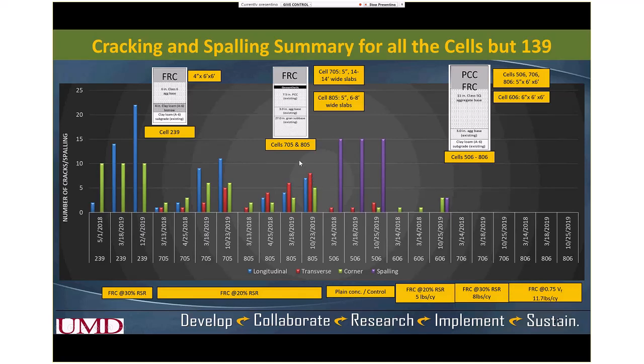But overall, the wider slab resulted in more number of cracked slabs. On the other side, where we varied the fiber, 506 through 806 did not show a lot of cracks. Only 506 has shown some cracks. I think it was only 3 cracks in the last year.